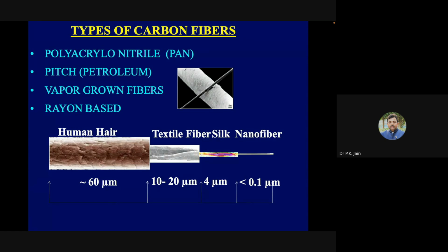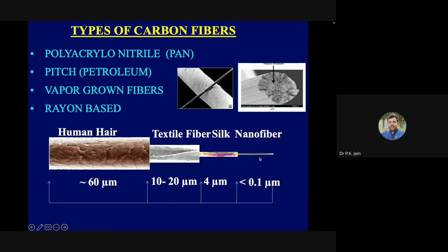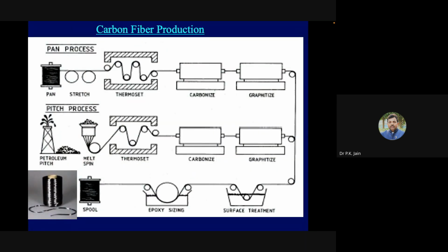Now, carbon fiber is made from a few sources like polyacrylonitrile, pitch, vapor grown, or rayon based. If you compare with human hair, this is the nanofiber. This is how the microstructure looks. Carbon fiber is made by this technique where you take the PAN-based polymer fiber and stretch it, which is called the stretching or stabilization process, then carbonize it and graphitize it, and finally give a surface treatment, and then you get the commercial carbon fiber. Another way is to use coal tar pitch, which is a byproduct of the petroleum industry, and you draw it through a spinning process, and that fiber you carbonize and graphitize, and that gives a very high-end carbon fiber, which is used mainly in the aerospace industries.